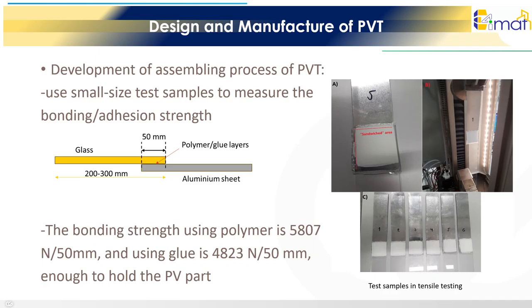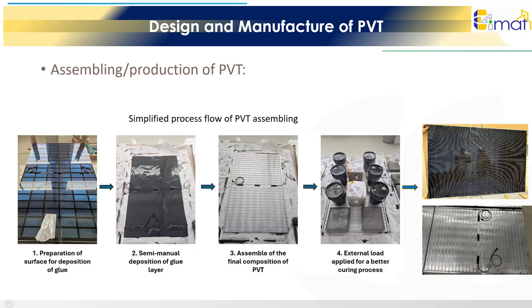Such small-size test samples are tested in a tensile or stretching machine to determine the adhesion strength. In addition, the small-size test samples could be placed inside the climate chamber for durability tests. The bonding strength using polymer is 5,807 Newton per 50 mm, and using glue is 4,823 Newton per 50 mm, which are enough to hold the PV part. The PVT process is semi-manual, but with additional equipment related to glue dispensing and mechanical pressure it can be automatized.